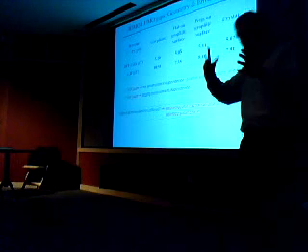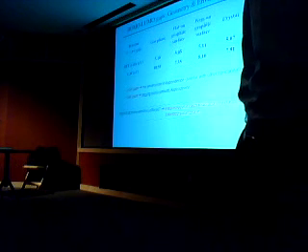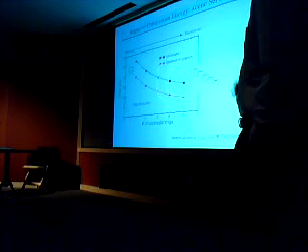However, the GW calculations show that there is significant dependence on geometry because it's related to the correlation of the electrons, the quasi-particles in the molecule, with the electrons on the surface. So this kind of change from the LDA value comes from intermolecular exchange and correlation, and also interfacial polarization. And here I just show you that this kind of effect doesn't go away with bigger molecules.